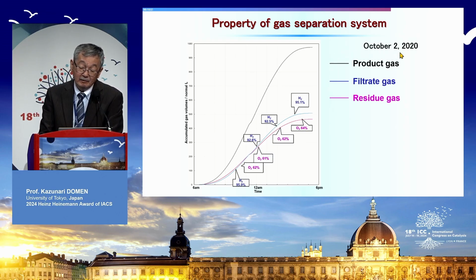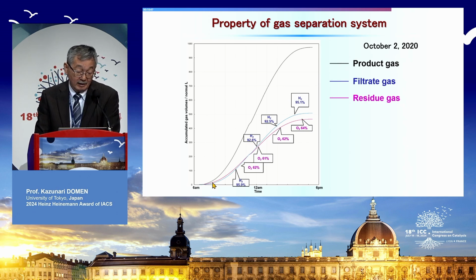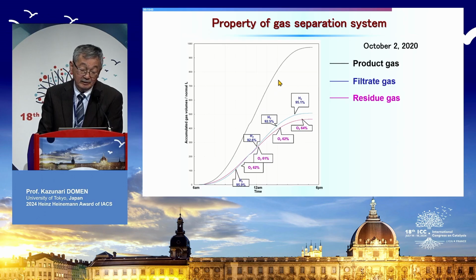This was carried out October 2nd in 2020, and this is almost a clear day. And this is the accumulated amount of evolved hydrogen and oxygen. In this case, we obtained almost 100 liters of hydrogen and oxygen mixture. And this curve is a little bit complicated, a busy one. But this blue curve is hydrogen-rich filtrated gases.